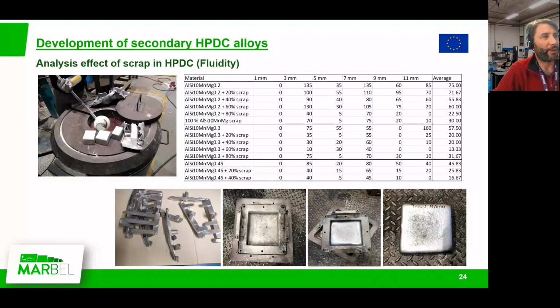And what we have done, as for high pressure die casting, one of the most important properties, especially for formability, is fluidity. We have developed a fluidity test to analyze the impact that the scrap has on the fluidity. Without any previous melt treatment, what we observe is that by increasing the amount of scrap, we are losing quite a lot of fluidity.